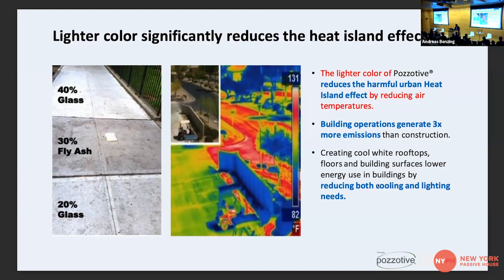Another good benefit of it, when you take mixed recycled glass, clear, brown, and green, on average, about 60% of MRF glass is clear. And then the others are mixed between brown and green. When you mill it, it becomes bright white. On a scale of 1 to 100, it's about a 90. So it's extremely white material.